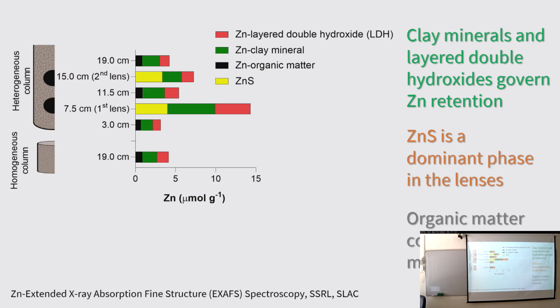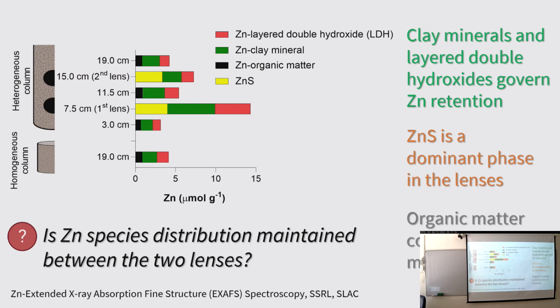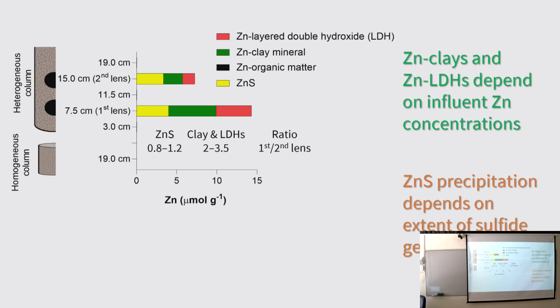Here I'd now like to come back to the difference in the loading between the first and the second lens, and ask the question: is the zinc species distribution maintained between these 2 lenses? I've hidden the results from the sand, and we're only focusing on the 2 lenses, looking at the ratio between the first and the second lens for each of these zinc species. For zinc sulfide, you can see that the level was maintained relatively the same between the first and the second lens. However, for the clays and layered double hydroxides, the loading was doubled in the first compared to the second lens.